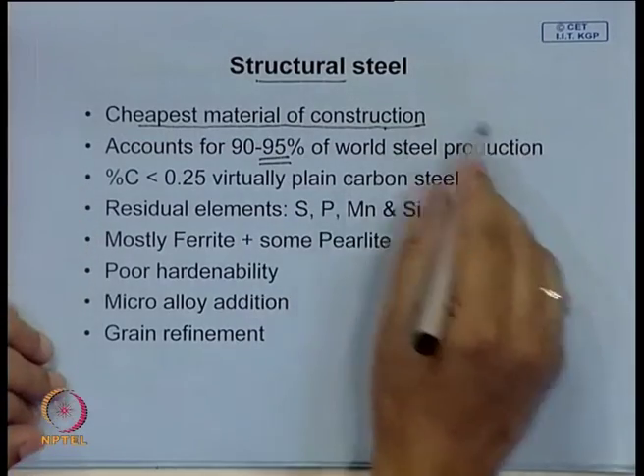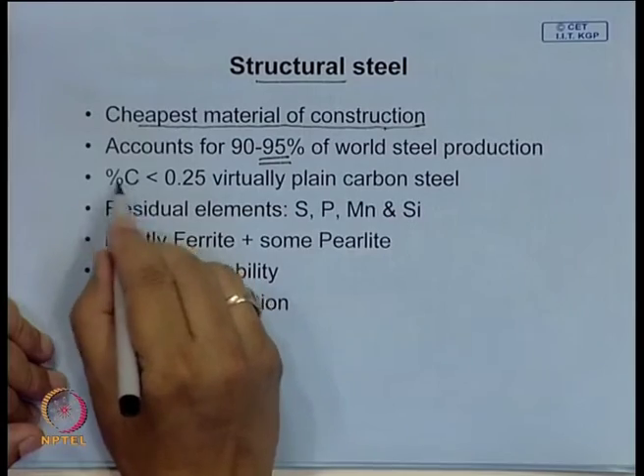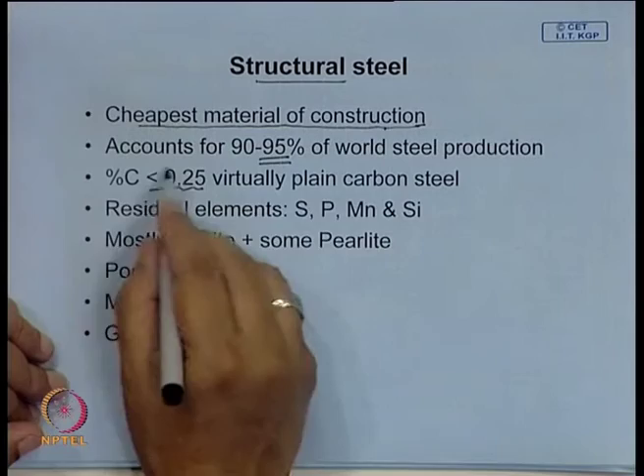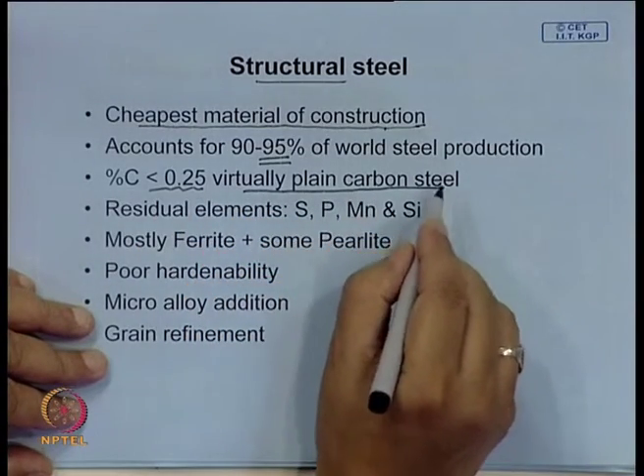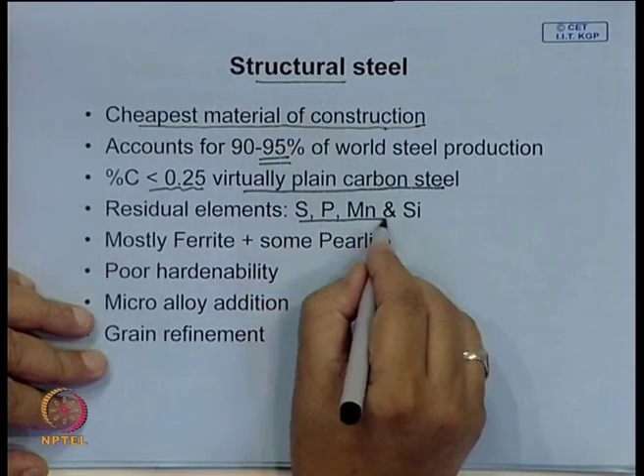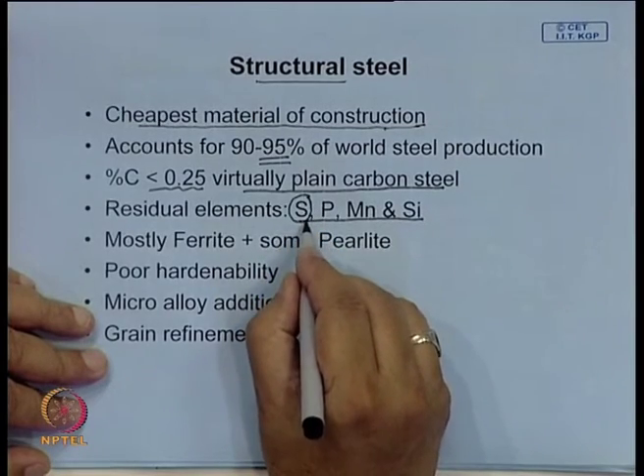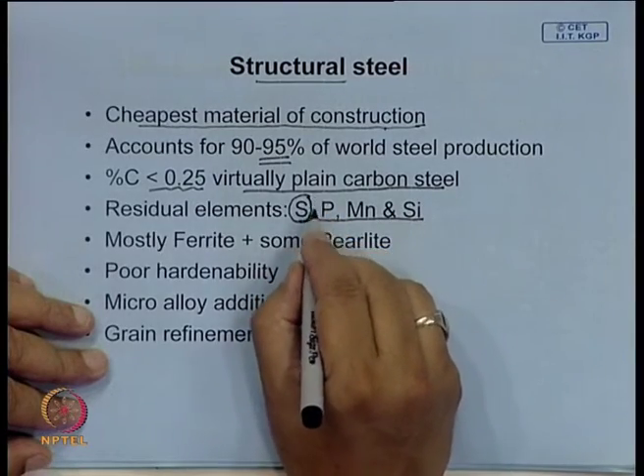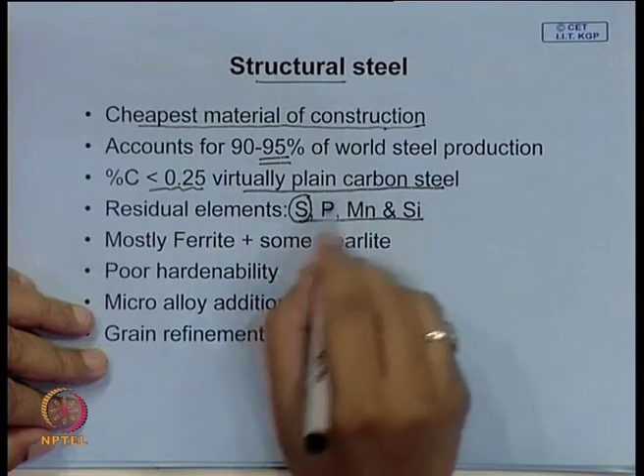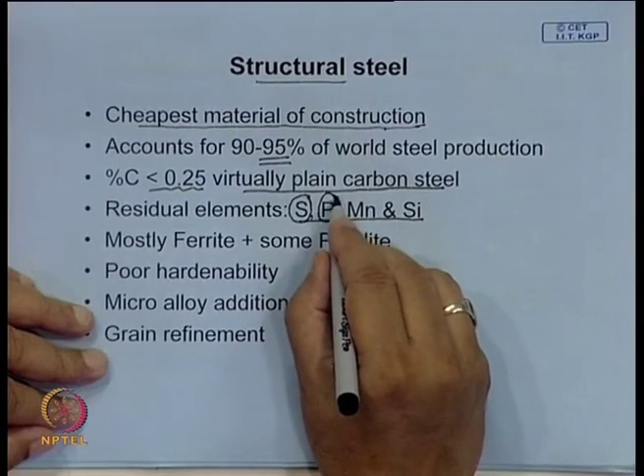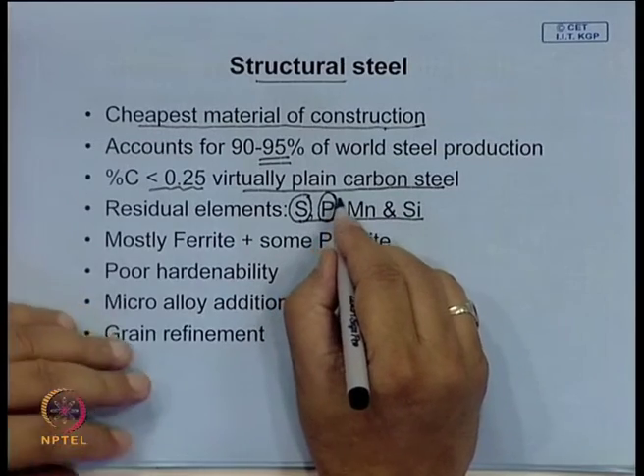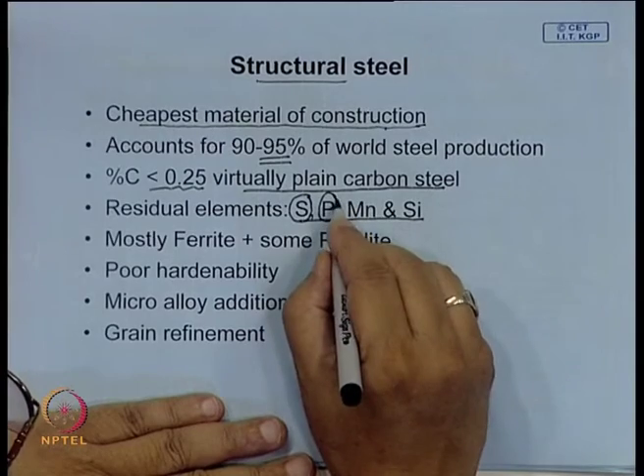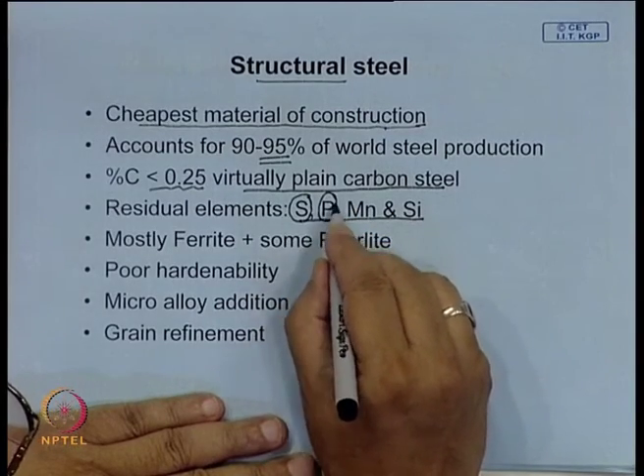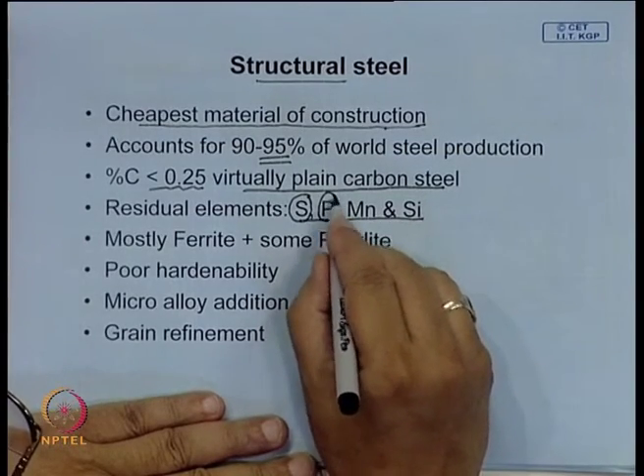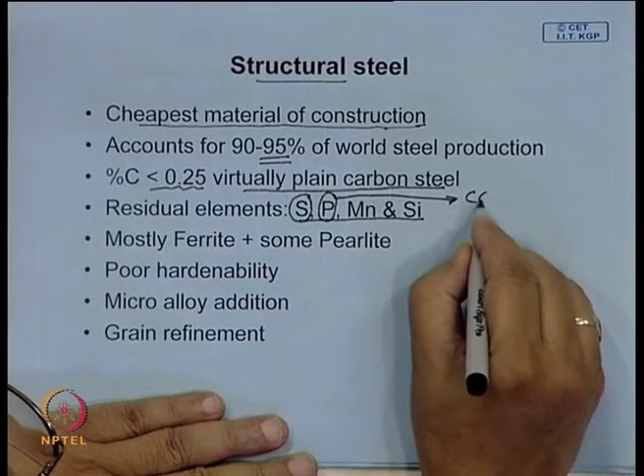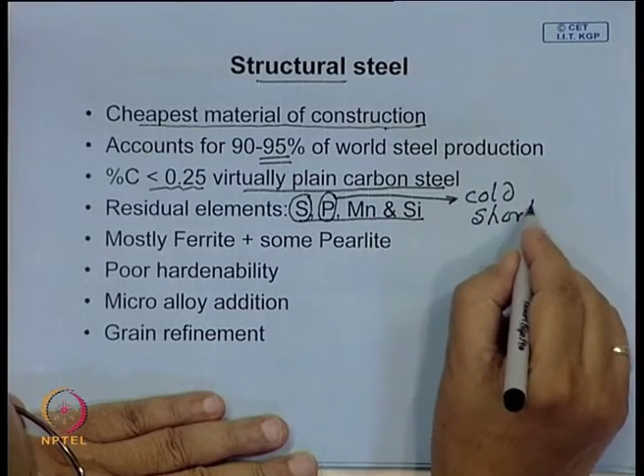Bulk of this production actually is for structural steel, and we call any carbon steel less than 0.25, rather relatively low, virtually plain carbon steel. It has some residual elements which are not intentionally added, which are listed here. Sulfur is undesirable, it gives hot shortness, makes hot working difficult, and to overcome this some amount of manganese is added to steel. Phosphorus is also detrimental. It has a very high hardening coefficient, it increases the strength of ferrite significantly, it is a very important solid solution strengthener for ferrite, but it segregates to grain boundary and makes the steel brittle, and it is responsible for cold shortness. It is brittle at low temperature.